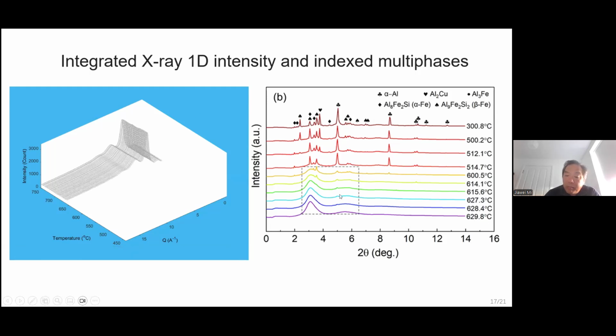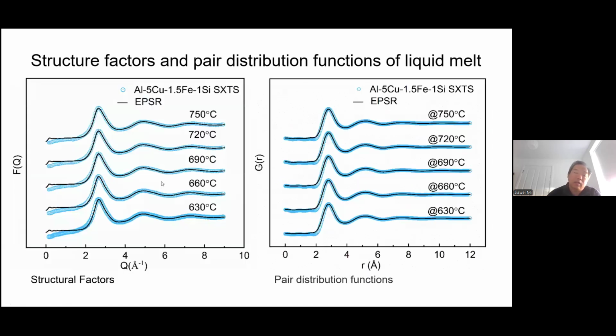But for the pre-nucleation atomic structure, we are mainly interested in this kind of regime, just before you have a tiny crystal appear, and how the liquid structure changes. As I said, by only looking at this I(Q), we cannot get much more useful information. We have to convert this I(Q) versus temperature into the so-called structure factor and the pair distribution function using Fourier transformation. When you look at the pair distribution function, carefully looking at the change of the peak position and the change of the peak height, you can get quite detailed information.